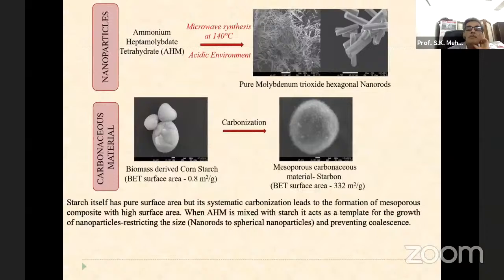So she used microwave synthesis, taking ammonium heptamolybdate, and in an acidic environment, she could create pure molybdenum trioxide hexagonal nanoparticles, nanorods. Along with it, a carbonaceous material, which was biomass-derived corn starch, because as in the previous work I've shown you, he used corn starch. But we found that the BET surface area is only 0.8 meters squared per gram. But when we have carbonization, that is, carbonaceous material is prepared, which is mesoporous, you have a surface area of 332 meters squared per gram. So as you can see, the surface area increases very high.